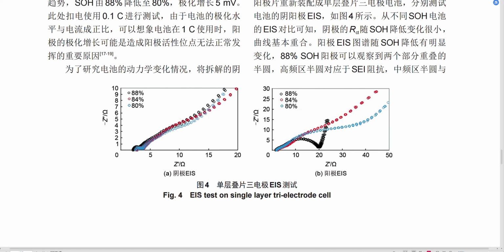So what they have done is a single layer full cell. Actually, it's a single layer 3 electrode cell. So they do the EIS measurement for those 3 electrode cells. And Figure 4A is the cathode side EIS data. You can barely see any big difference in the charge transfer resistance, and also in the shape, for the cathode side EIS during the different SOH. And Figure 4B is the anode side, the graphite side EIS during the different SOH.